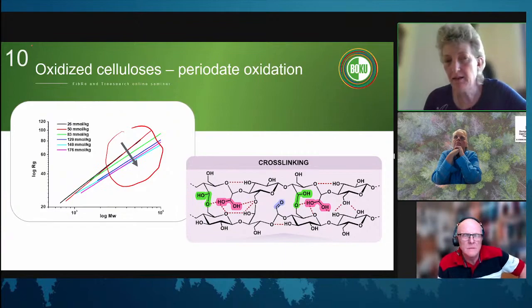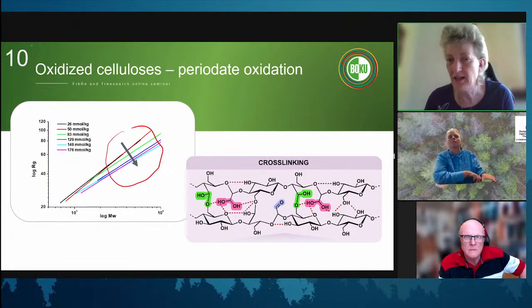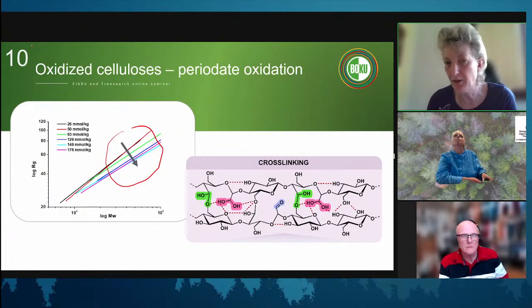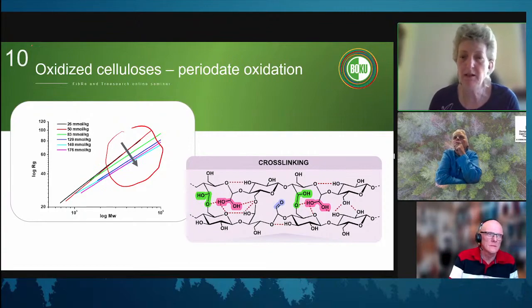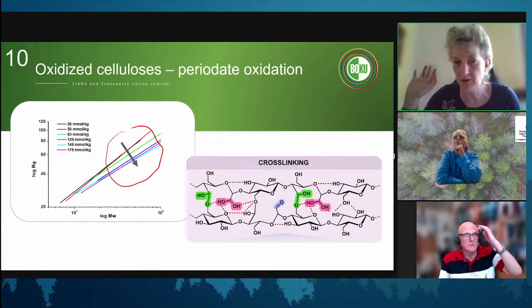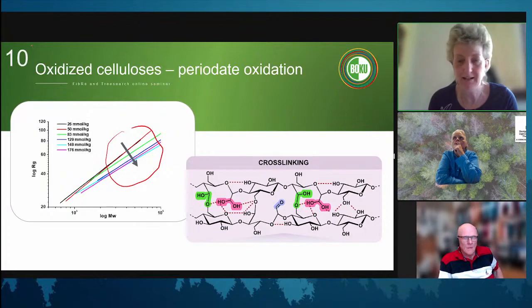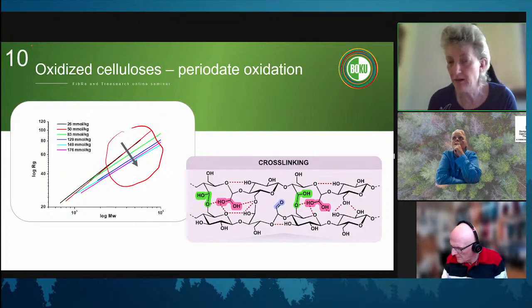Okay. The problem is if you heat your sample and reach a state where, when you cool it down, it stays in solution, that would maybe help. But heating up something in dimethylacetamide/lithium chloride, which is our solvent, is not a good idea because as an intermediate, you form something. There's a publication from us on that long time ago. You form a species which cleaves your glycosidic bonds. So heating DMAc/LiCl is nothing we do. We run everything really at room temperature, maximum 35 degrees.